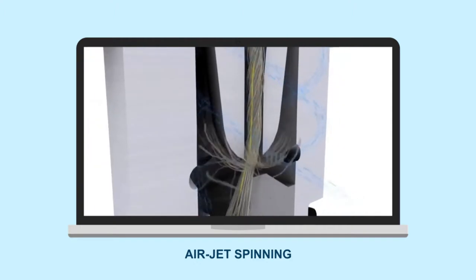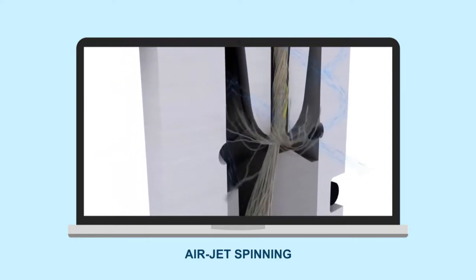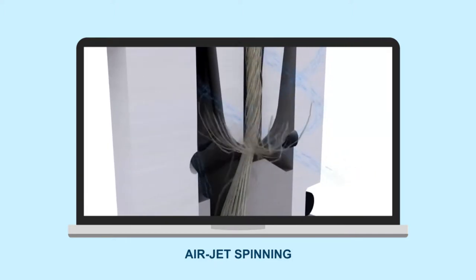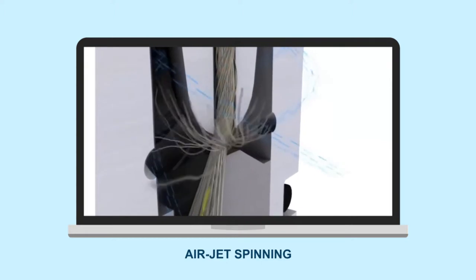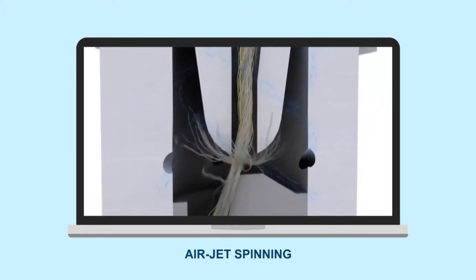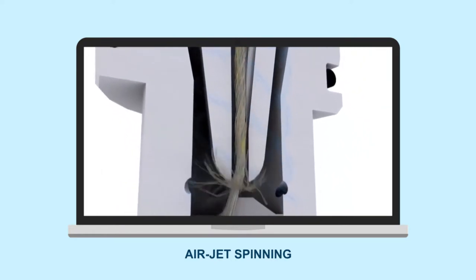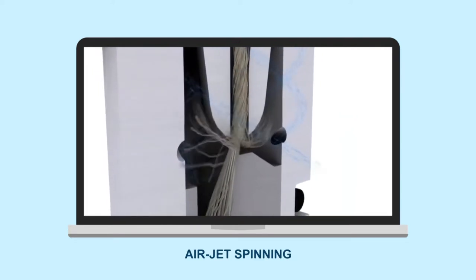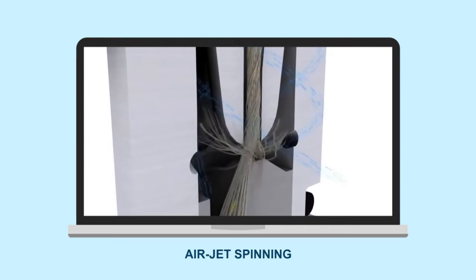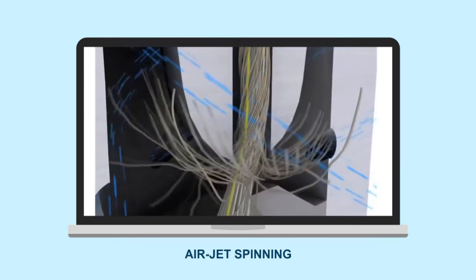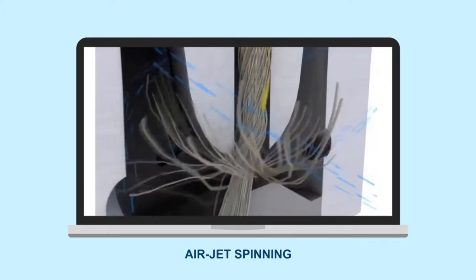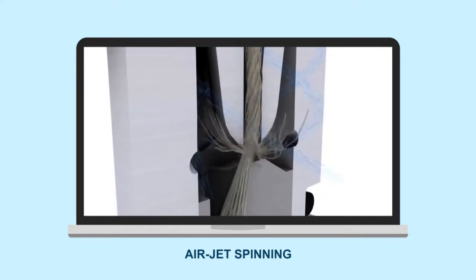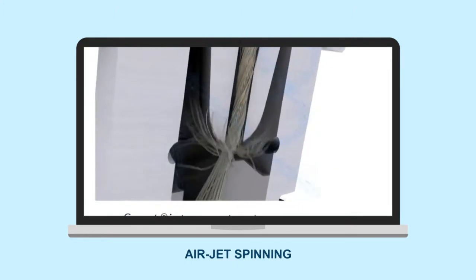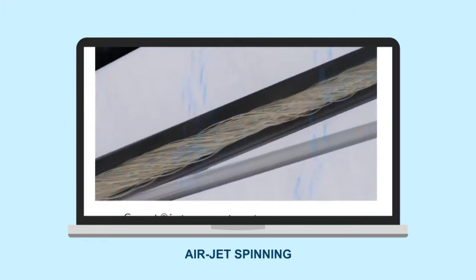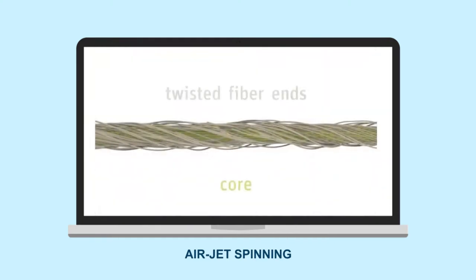The front part of the fibers enters the tube of the spinning tip and creates the core of the yarn. The four air jets in the twist element create a whirlwind around the spinning tip by means of pressured air. The air drifts the loose fiber ends around the spinning tip. With the spinning speed, the wrapped fiber ends are pulled inside the tube and they are twisted around the yarn core. The comfort jet yarn structure shows parallelized fiber mass forming the core of the yarn, and the fiber ends twisted around the core. The yarn surface is smooth and even, and shows a low value of yarn hairiness.